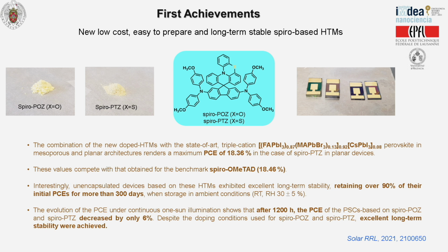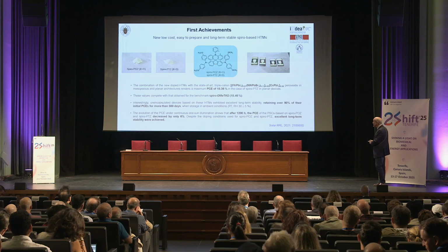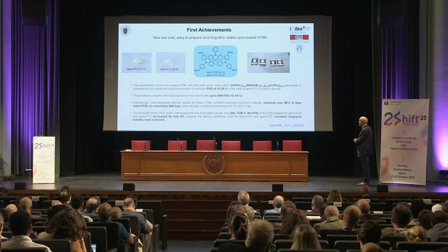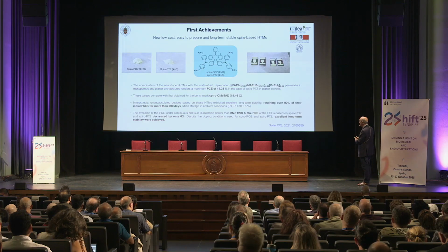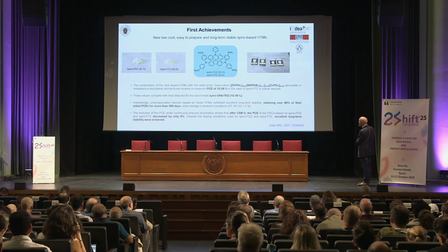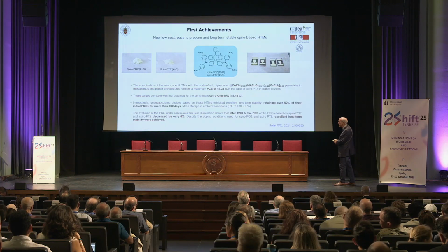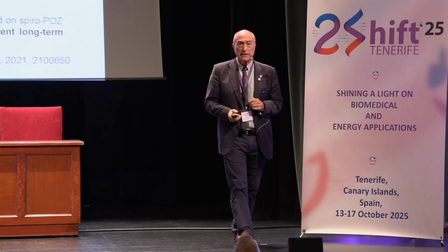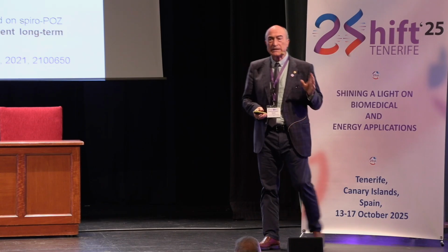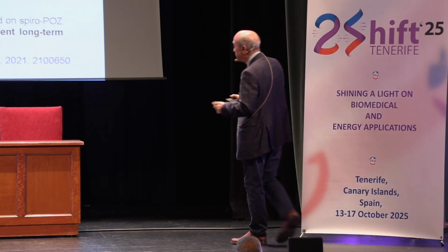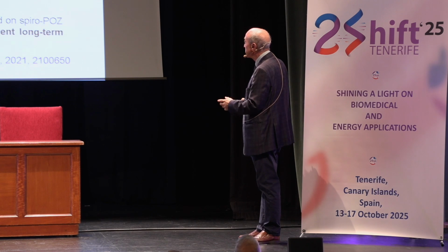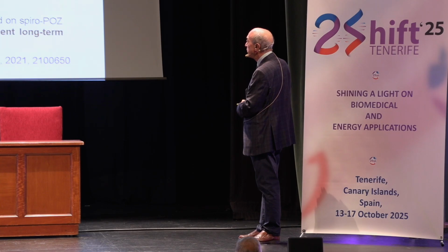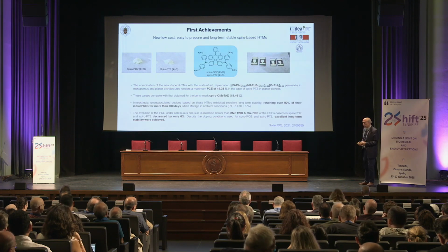Spiro-OMeTAD was pretty much the same. But notably, these systems improve drastically the stability of the cell, because you can see here that our system was able to retain over 90% of the efficiency for more than 300 days. So it was around 1 year, and the stability was surpassing 90%. This is something completely unusual, never seen for OMeTAD. And this was at ambient condition, room temperature. This is the humidity, relative humidity, 30%.